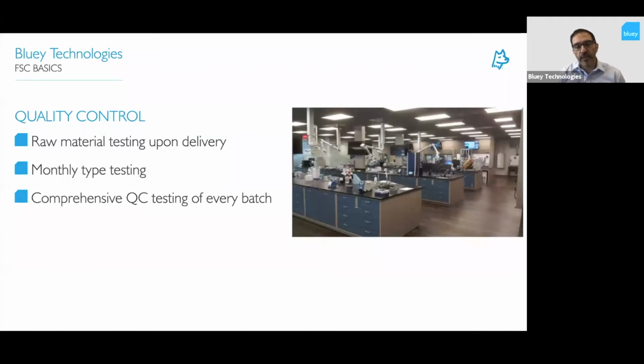Every month, we're pulling out all the raw ingredients and we're doing type testing. Now, type testing is something you would normally do once when you develop a product, but we're now doing this every month. The reason for that is so that we can have constant data on the raw materials we're using in advance of them being applied on site. So we will already have the 28-day strengths before that product is manufactured and sent to site, which means that we get much more reliability and can identify trends and patterns in the raw materials over time.